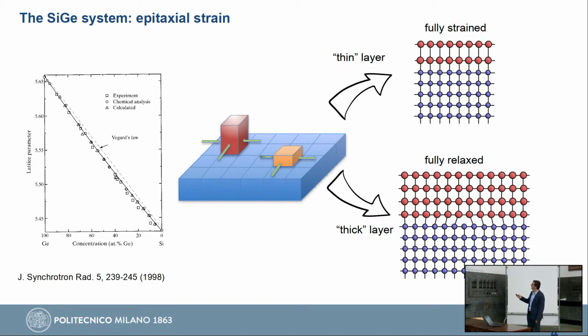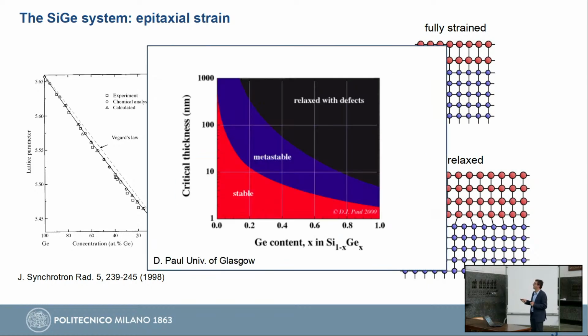And so in this case, I will have a relaxed silicon layer, and on top of it, a plastically relaxed germanium layer, where essentially I don't have any strain anymore. And these two ingredients are actually relevant for the application that we will see. So what does it mean, thin and thick? Actually, you can make a very simple calculation, which is based on this energy balance between the elastic energy you need to store in your system and the energy required for nucleating defects.